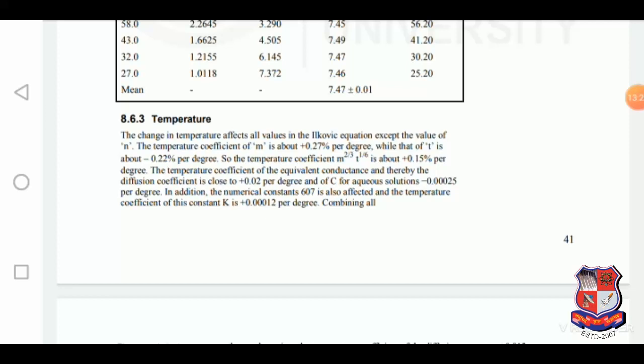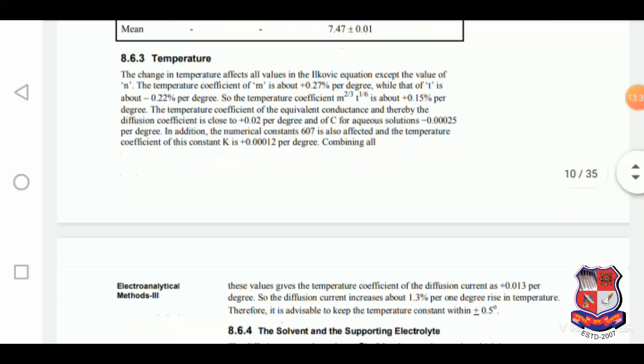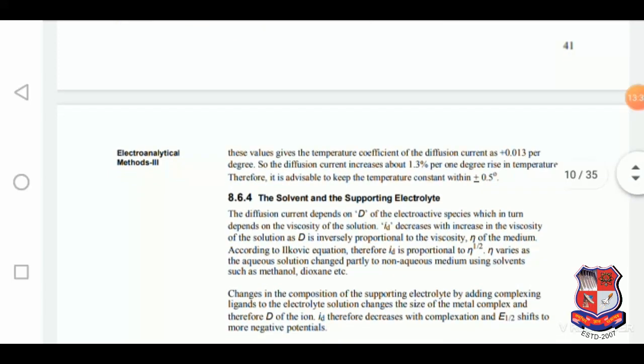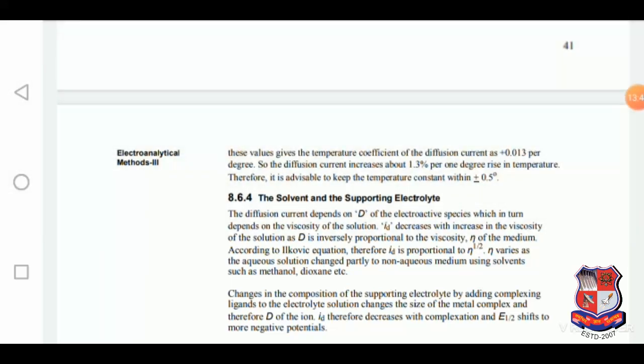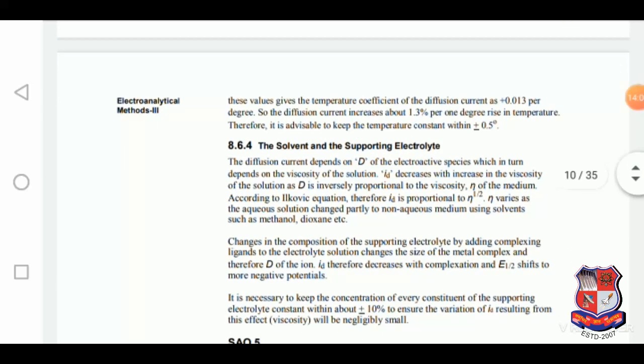In addition, the numerical constant 607 is also affected, and the temperature coefficient of this constant K is 0.00012 per degree. Combining all these values gives the temperature coefficient of diffusion current as plus 0.013 per degree. So the diffusion current increases about 1.3% per 1 degree rise in temperature. Therefore, it is advisable to keep the temperature constant within plus or minus 0.5 degrees centigrade.